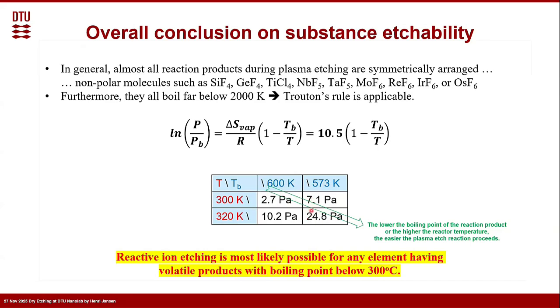Even this one. But for that reason, and we know that this is true for everything because we just said it, this is Trouton's rule: if we see a boiling temperature below 300 degrees, that means our product is going to be volatile at the reactor pressures we are going to use, let's say 10 millitorr, and with our reactor at 20 degrees, it will work.